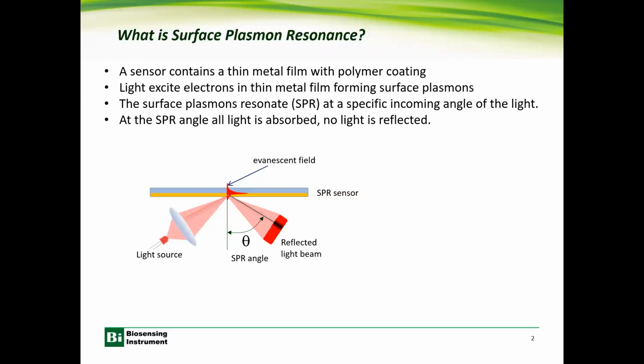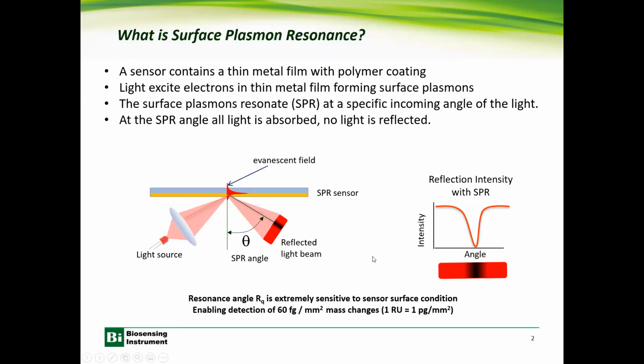So when you detect the reflected intensity, you will see a dark band or a minimum on the detector. This special reflection angle is called the SPR angle or SPR response. And this angle is extremely sensitive to the surface condition, and particularly sensitive to the dielectric properties of the interface, which can be affected by many different processes such as adsorption, desorption, chemical reactions, surface electronic states, and density and thickness of the film, etc.